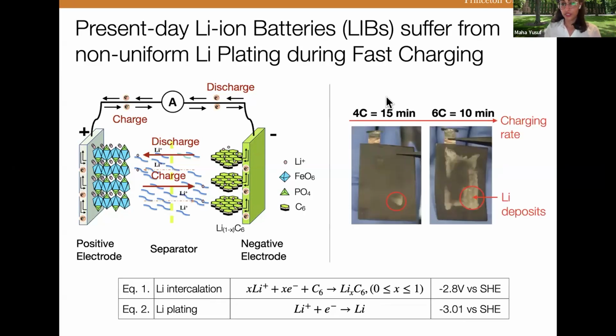Here I'm going to show you these optical images of two custom-made battery pouch cells that were charged between 10 and 15 minutes. And you can see deposition of this whitish material on the surface of this battery anode. So this whitish material is lithium metal or lithium deposits. And this process is called lithium plating.